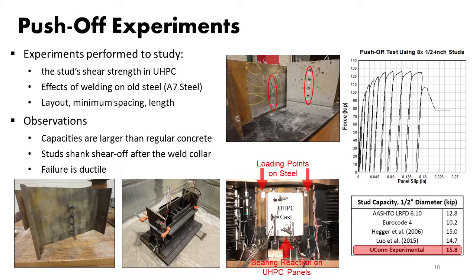During the second phase, we are studying the effect of different patterns, layouts, spacing, and length of studs, and specifically focused on welding of studs on old steel, because there were some concerns about the weldability of these studs to A7, which is typically the material from the 50s, 60s. We were given some floor beams from the Q-Bridge. I don't think that exists anymore. And we had some issues with cleaning the lead paint, and ultimately we were able to clean the beams, and we are using pieces of those to test our stud capacities.